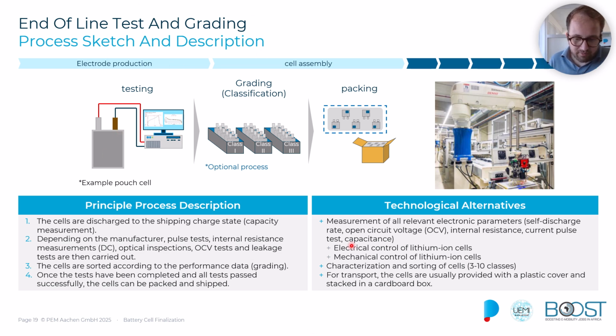So you see here a typical process sketch of an end-of-line testing and grading station. All cells are brought to a certain level of state of charge, the SOC. They are measured, for example, depending on the manufacturer, with a pulse test, internal resistance, optical inspections, the OCV, the open circuit voltage, leakage tests, and further tests can be carried out. Also, a lot of optical pictures can be taken here. Then they are sorted and graded according to their performance, and once they have been tested and pass successfully, they get packed and can be shipped.